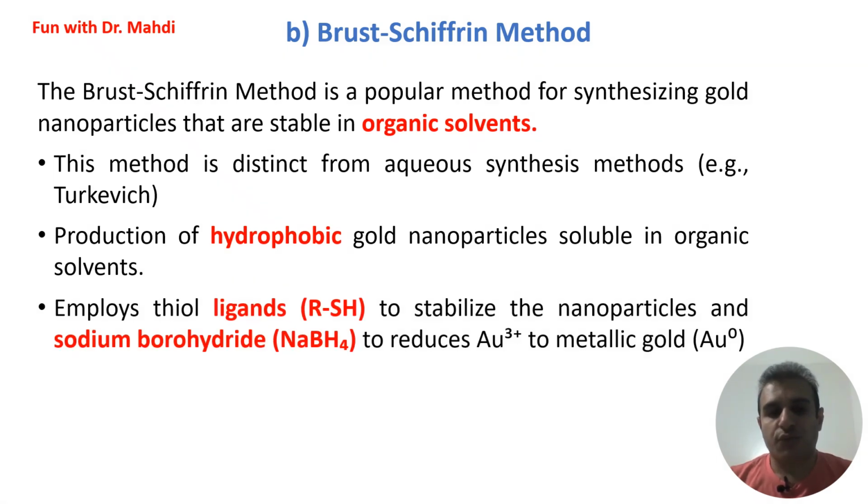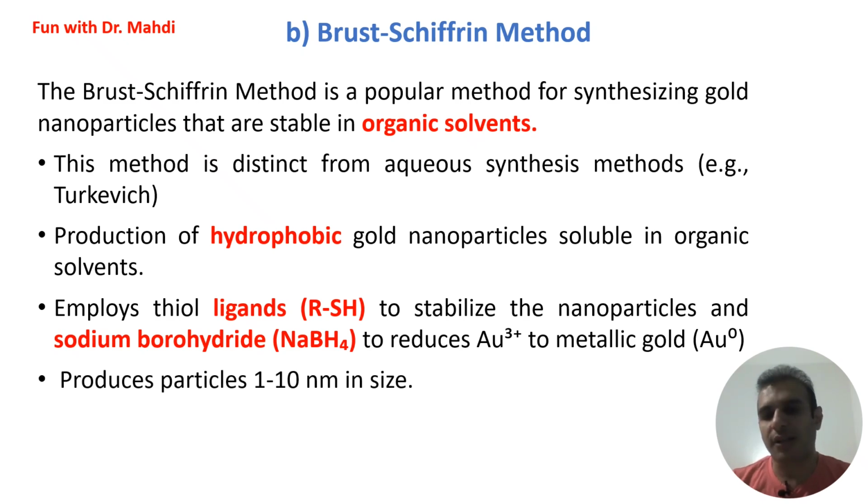And also we need to use a stabilizing agent. We need to use thiol ligands as a stabilizing agent, and also we need to use sodium borohydride as a reducing agent in the Brust-Schiffrin method. And the size of nanoparticles in this method is between 1 to 10 nanometers.